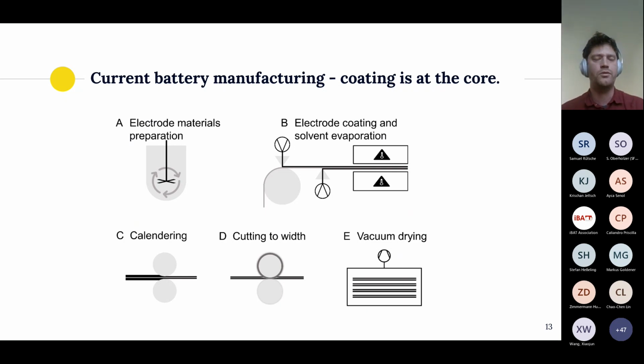And at this point, I would like to briefly introduce the typical battery manufacturing steps as they are being followed in today's factories. And this typically starts with a mixing process, right? The active materials are combined with binders, conductive additives, with a suitable solvent to produce a slurry, a material that can be pumped and dosed at the coating station. And at the coating station, you typically have a substrate that functions as the current collector itself. And in many cases, the current collector is coated from both sides simultaneously, so that you can produce here, we have an aluminum current collector and a cathode material, your cathode electrode.